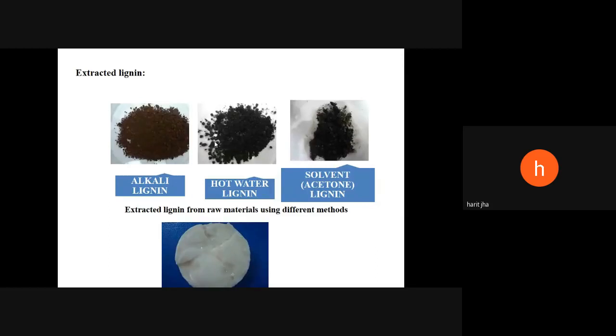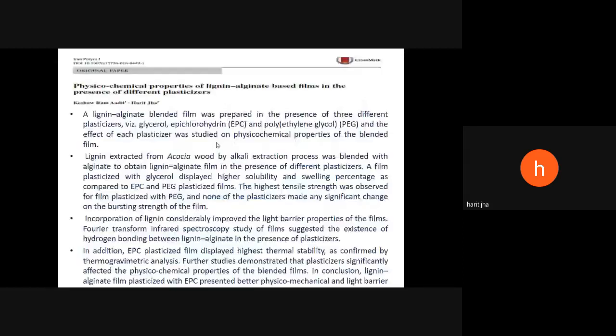Now, one of the applications of the work which we have done is one in which the physicochemical properties of lignin alginate based films were prepared, and their properties were assessed in the presence of different plasticizers. Okay. Now, a lignin alginate blended film was prepared in this work, in the presence of different plasticizers like glycerol, epichlorohydrin, and polyethylene glycol. And the effect of each plasticizer was studied on the physicochemical properties of the blended film.